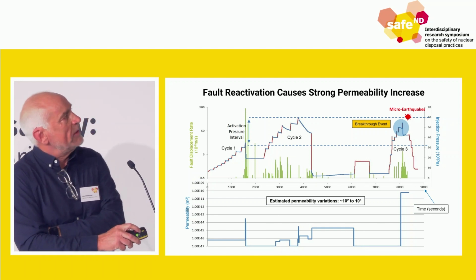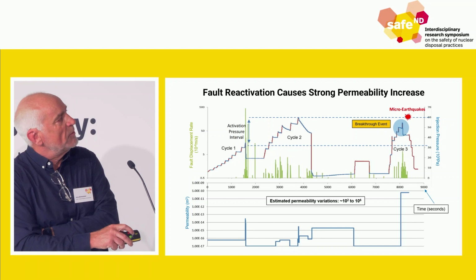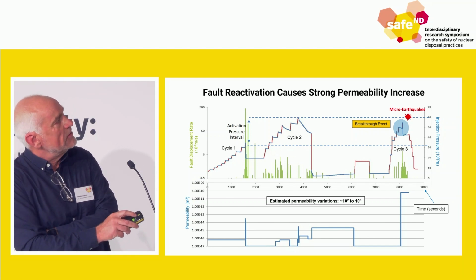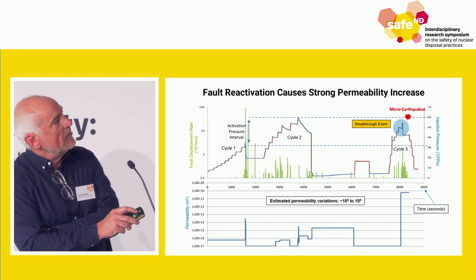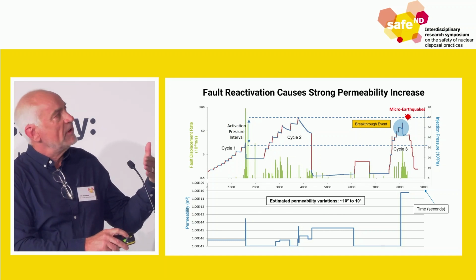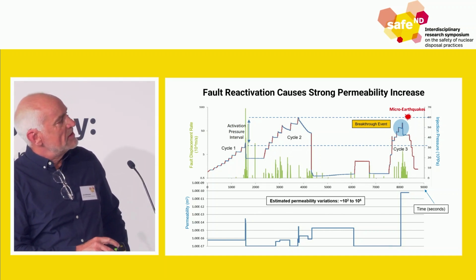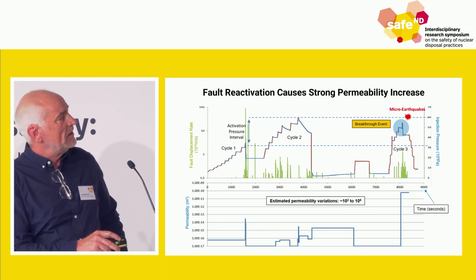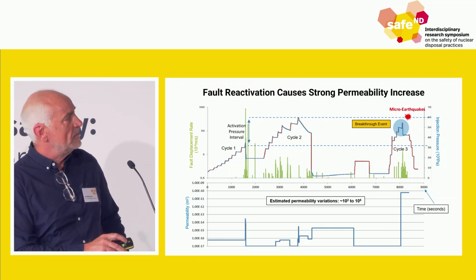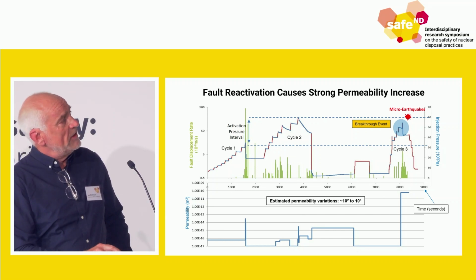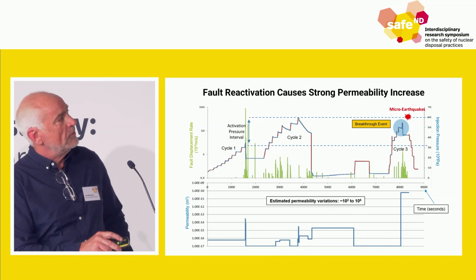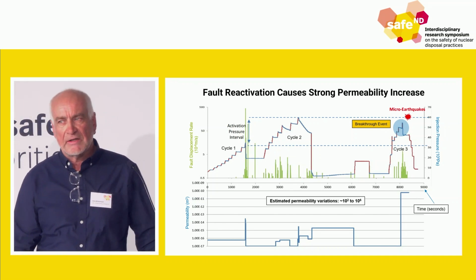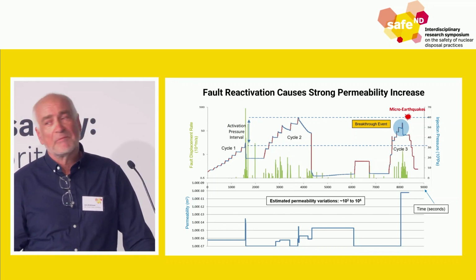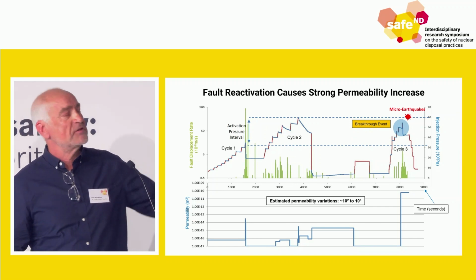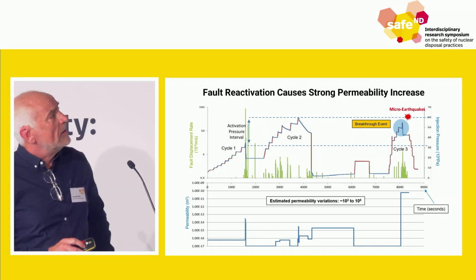Here, first of all, we looked at what kind of permeabilities might have been generated, and we calculated that from the pressure fall-off as we stopped injecting stepwise. The initially very low permeability, and this is a first-order estimate, did increase quite a bit. Particularly when we had this breakthrough, we got probably 5-6 orders of magnitude increase. So that could be performance relevant if it was to continue over time.